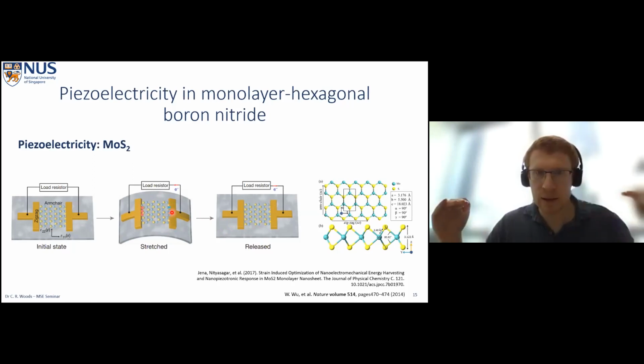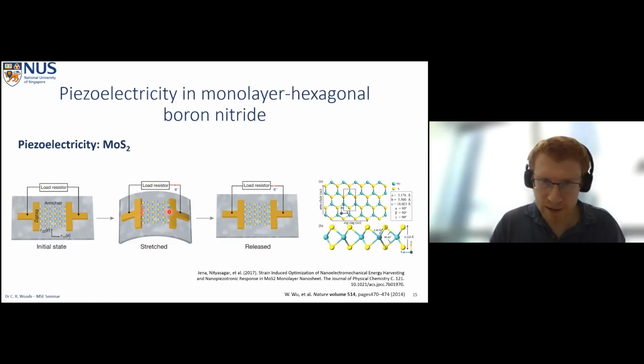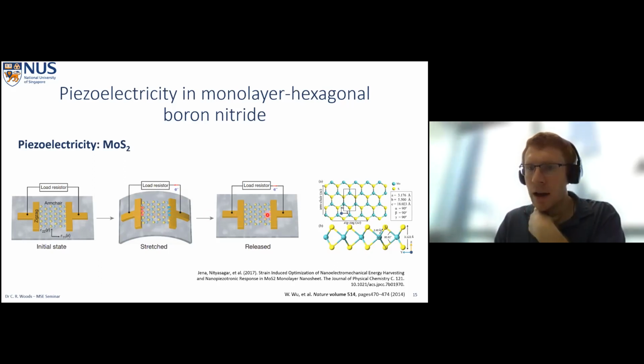Well, if I leave my polymer flat, then I have a straight line. So this is the shortest distance. But then if I bend my substrate and I have that same distance, but I now have to follow a curvature around, then this distance across the polymer layer will be bigger. And this causes the strain, because the crystal has to follow this much longer path. So this causes the strain in the crystal.